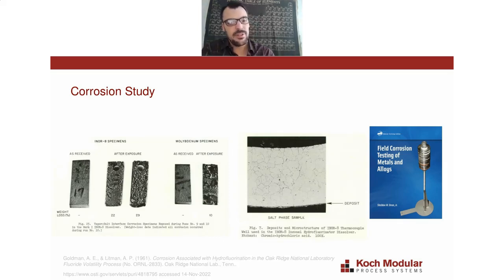and probably qualitatively on their own can be discounted as used for construction and scale up. However, some of the more modern alloys may show little, if any, tarnishing or damage, and so we determine whether or not they are suitable based on weight difference, weighing the coupon before it goes in, weighing the coupon after it comes out of a 200-hour corrosion exposure. You have to be careful when you do this, however, because there may be deposits on the metal, a film or an oxide or an adherent layer, and it could be the case that the amount of metal loss is roughly equal and opposite to the amount of mass gain from deposits, and that will give the impression that you don't have a corrosion problem.